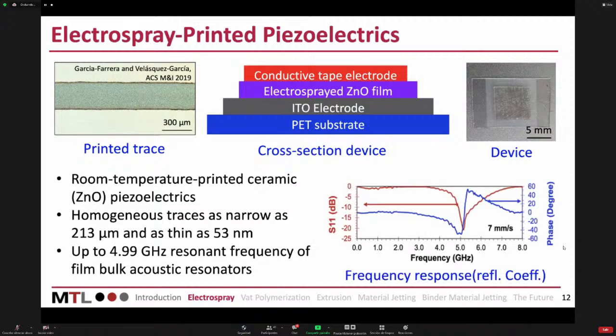What I'm showing here is the reflection coefficient, and there are 3 other coefficients for when you operate with RF. But the key insight is that you can see this sudden change that is telling about the resonance at about 5 gigahertz. So using fairly inexpensive hardware, you can create devices at room temperature that oscillate at 5 gigahertz, which is a lot faster than anything you can print. And what it's telling us is that the material you print, because it's electrosprayed and because it's so thin, is of the greatest quality. So you're able to create a resonating structure that has nothing to envy to something that is done in the clean room.